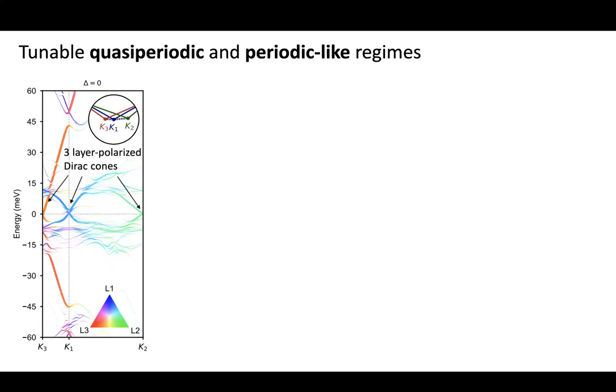So you can see that near the charge neutrality, we have three layer-polarized Dirac cones, and it looks like an approximately periodic structure. But then at higher Fermi energy, you have these spaghettis of flat bands. That is where the quasicrystallinity is being seen by the electrons. And then at higher energy, you still have this fast band from one of the layers, which has a larger angle, and it maintains more of its layer character than the others. So this region is going to look periodic-like to the electrons, and this region is going to look quasiperiodic-like, quasicrystalline.